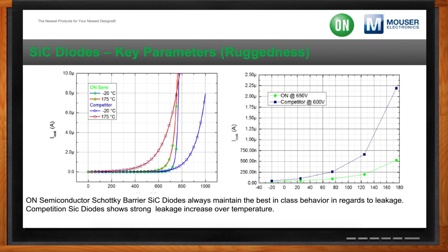So the first diagram here shows your leakage. And you can see that for a 650 volt diode, our design, which is the circles, has a very tight spread, which means that our design is very good. It hits at 650 volts and then it turns off. While some of our competitors have to have a very big design window because over temperature, they shift a whole bunch. The diagram on the right shows our leakage over temperature. So you can see as we heat up, we don't leak, whereas some of the competitor parts leak magnitudes greater than ours. So overall, onsemi's Schottky barrier diodes always maintain the best in-class behavior in regards to leakage.